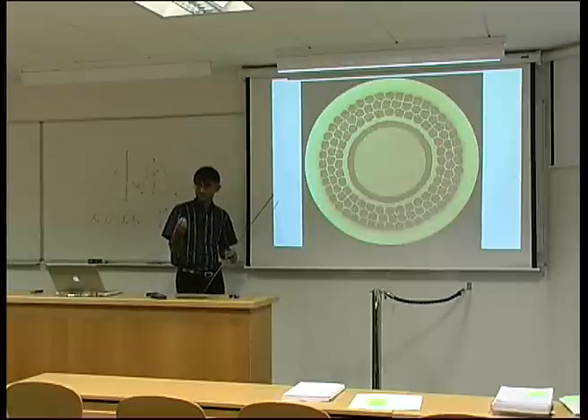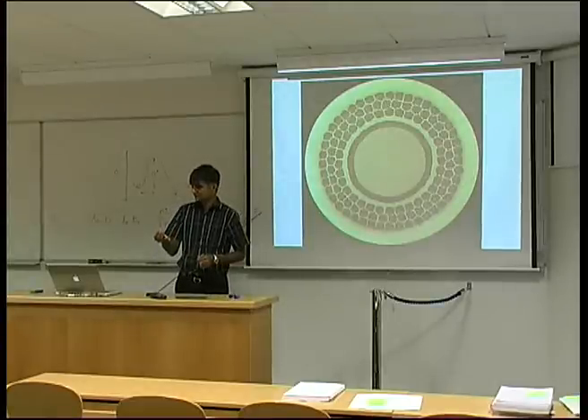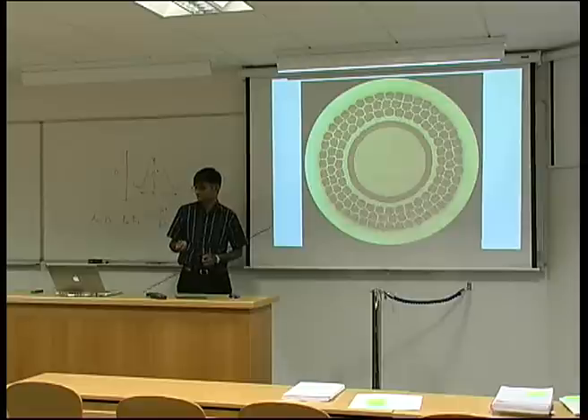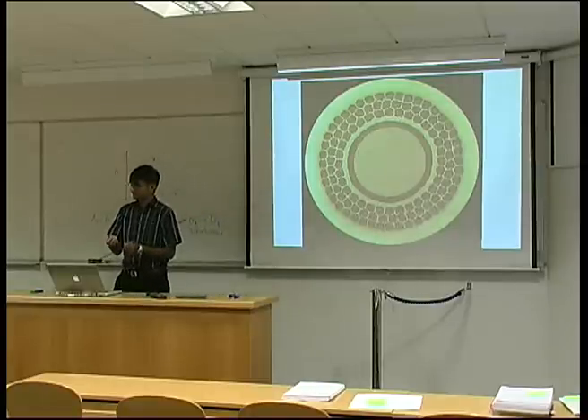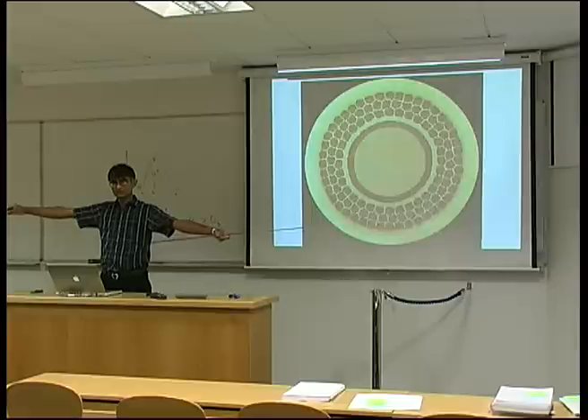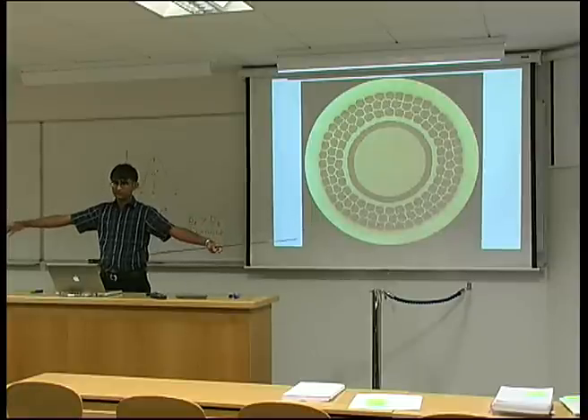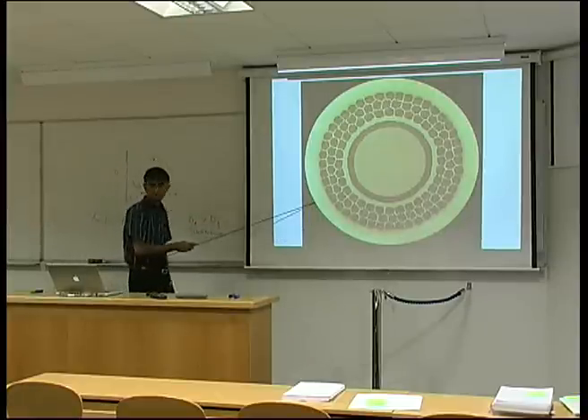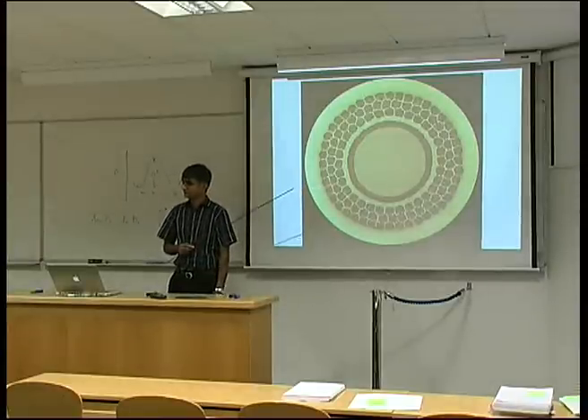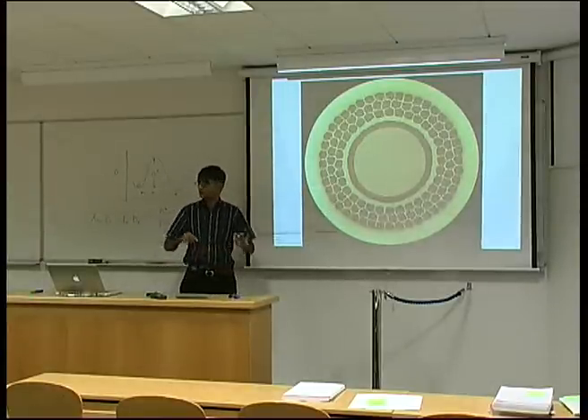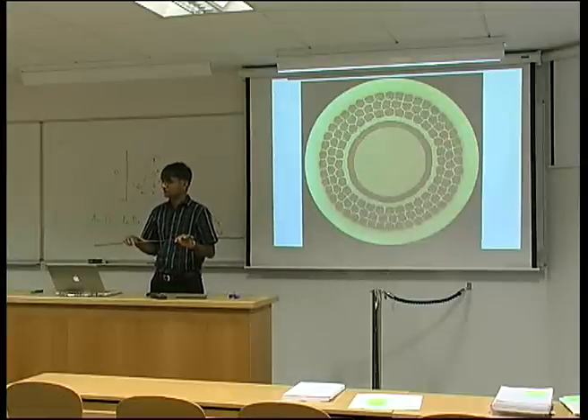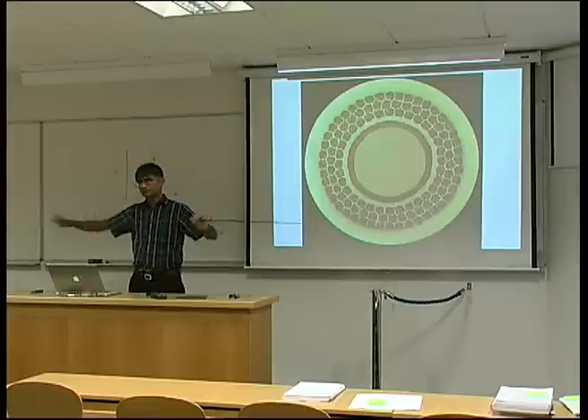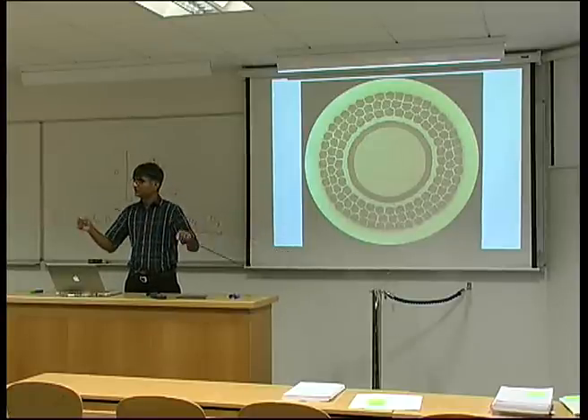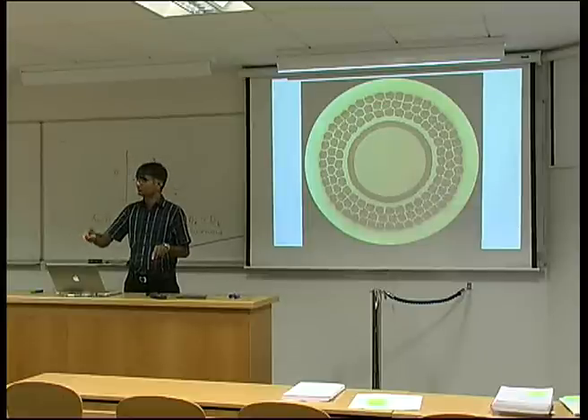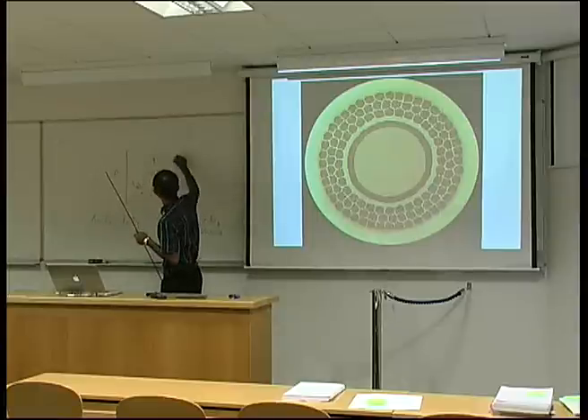Niobium tin, Nb3Sn, is a superconducting metal, a compound, but it's very brittle. So if you want to form cables of it, you wouldn't form it out of niobium tin. So what you do is you take bronze. Bronze is a mixture of copper and tin. You drill holes into it and you put niobium, which is a very ductile material like copper, and you draw it out into long wires. And then you allow diffusion of the tin to combine with the niobium to form the superconducting compound Nb3Sn.